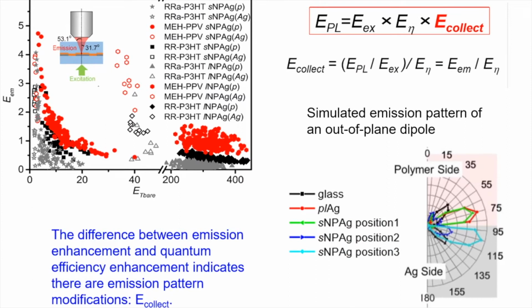The third contributor to the photoluminescence enhancement was changes in the emission pattern of the luminescence that were affected by the pores, and that resulted in a difference in collection efficiency of our system. So taking a look here at just the expression for the collection enhancement, written as a function of the photoluminescence enhancement divided by the excitation enhancement divided by the quantum efficiency enhancement, we can see that there are differences between the emission enhancement and the quantum efficiency enhancement, and that indicates that there must be emission pattern modifications as well.